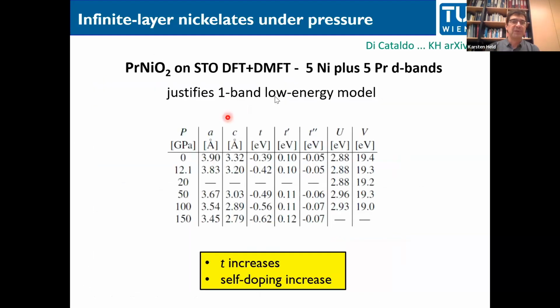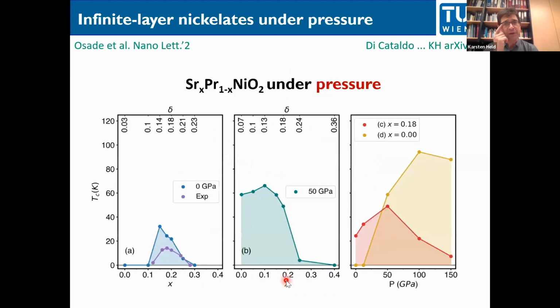So we have then done the same thing from the full DFT plus DMFT. We derived first the lattice parameters under pressure and hopping. The Coulomb interaction in CRPA doesn't change very much, so we kept it as a constant. And these are the 2 things that are really relevant in changing under pressure. We looked into 4 different paths. So first is the plane phase diagram without pressure and comparing with experiment.